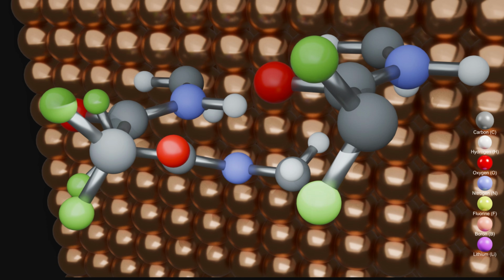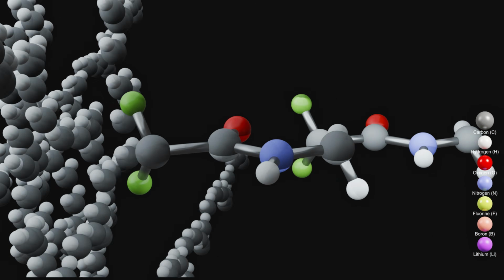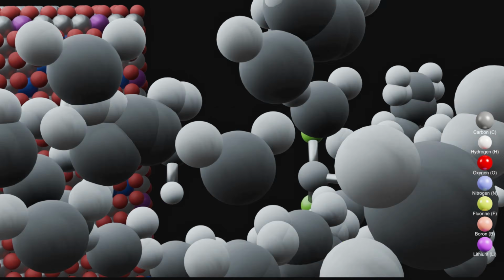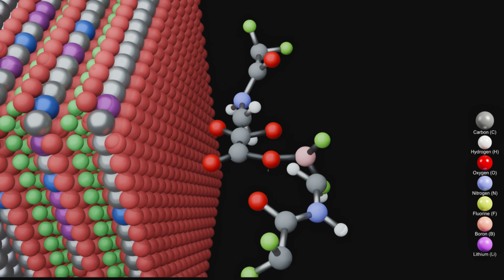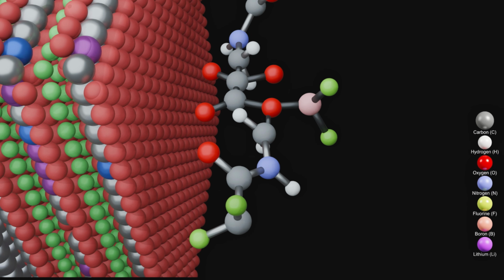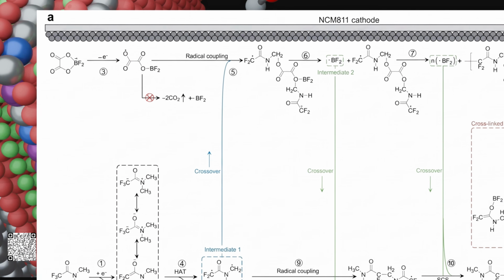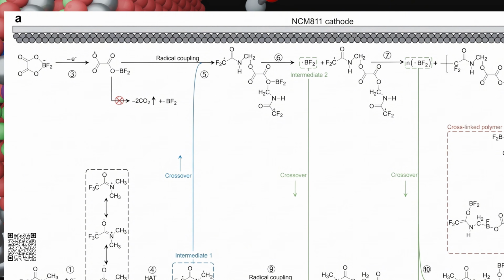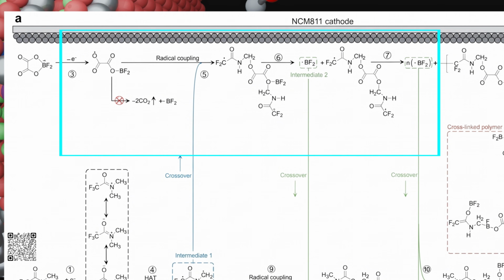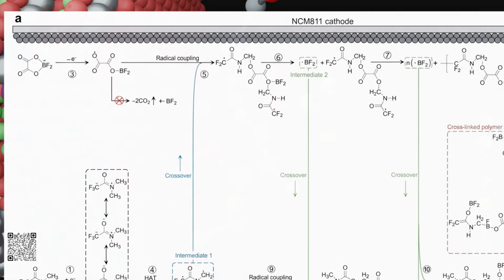This radical doesn't just sit there, it swims across the separator to the cathode. At the same time, the lithium difluoro(oxalato)borate salt at the cathode is trying to break down and release carbon dioxide gas. But the arriving intermediate 1 scavenges that breakdown product, effectively sealing the carbon dioxide pathway shut before it can bubble.